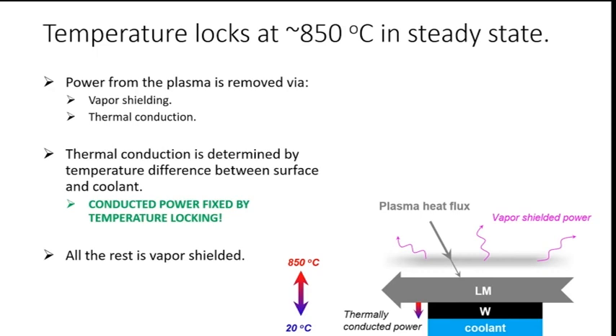shielding, right? Yeah, so you always end up around this 850 degrees C, but in theory, if you put a lot more power, it should be able to exceed this temperature, right? Because you will need slightly higher temperature to evaporate more particles to handle higher heat loads.